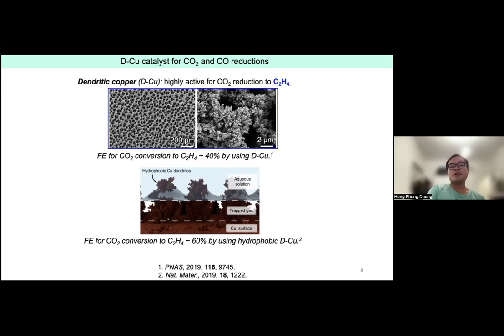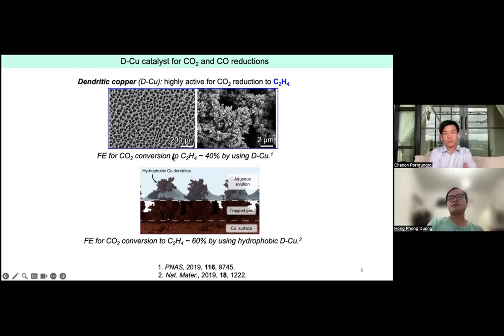And in our lab, in 2019, we had an idea to use a dendritic copper catalyst, and at that time we tried this dendritic copper, or DCu, I show here. The DCu was very good at making ethylene from CO2 conversion, reaching like 40% as shown. At the time it was quite impressive because it was 2019. And for this dendritic structure, we are still trying to understand why it is particularly good for ethylene.